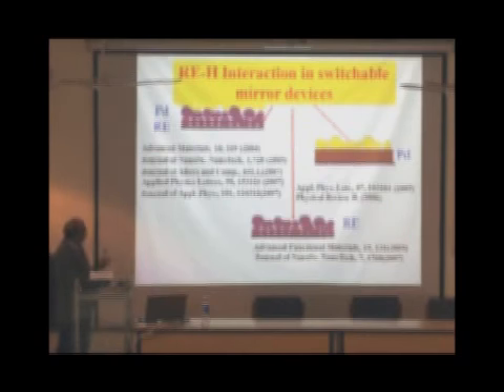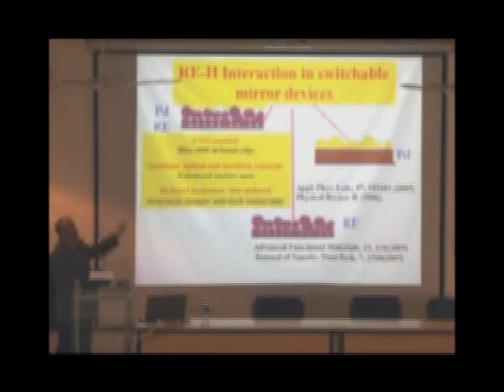The first system was that we made nanoparticles of one rare earth and we covered it with a palladium overlay, like in conventional devices. And what we observed is that all the properties which I mentioned as requirements for a good switchable mirror improve: the color neutral state improves due to the blue shift in the band gap, there is an increase in the optical and electrical contrast because of enhanced surface area, and there is a reduced hysteresis when you're putting hydrogen in and when you're removing hydrogen.